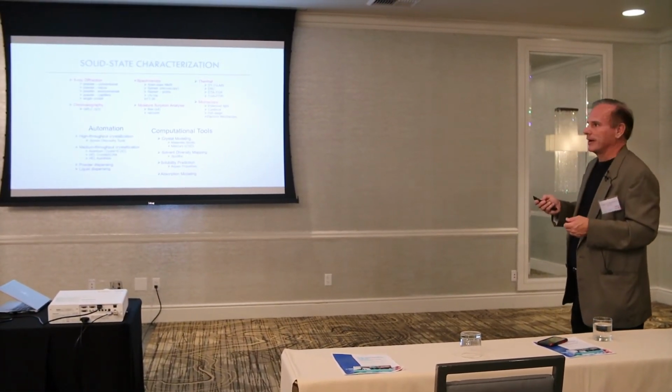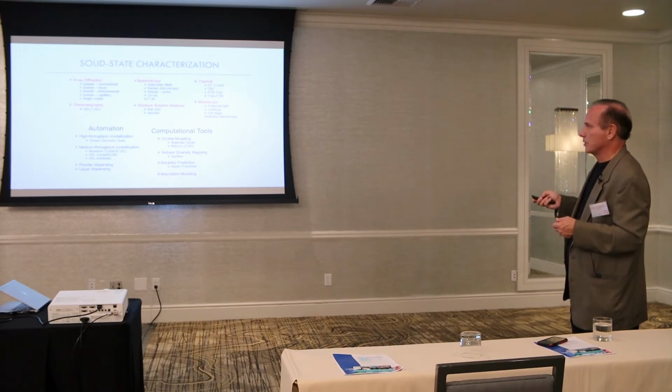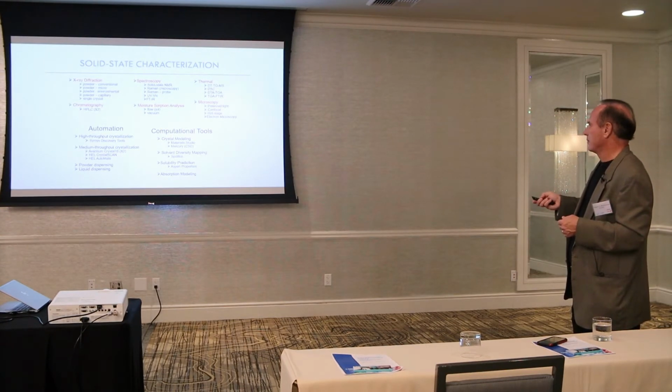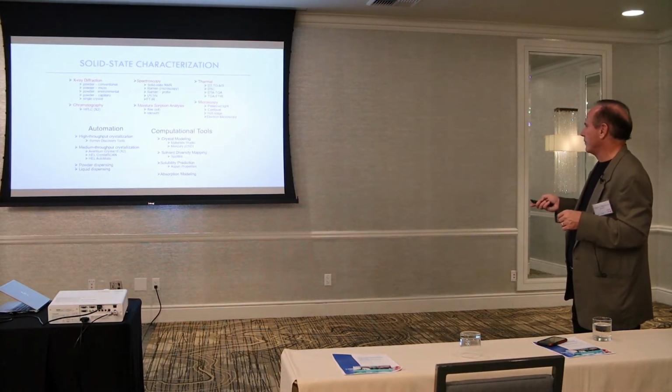If it's not equant, or if it doesn't look like it would be flowable, make sure there's enough three-dimensionality to it, or have them look until they find something that has an external morphology that looks like it might flow. Because I've dealt with this before, and it can be very challenging for your formulators. And it can cost a project a year or 2 in development.